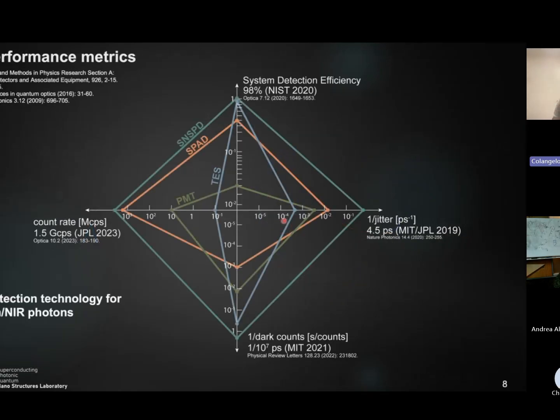Now, these are really, really amazing detectors. So they're the best detection technology for telecom and near-IR photons. And it's easy to claim. So here, I really like to show these plots where we have 4 detection metrics: the efficiency, the jitter, the dark counts, and the count rate. And these numbers here, not very important, but they're the record for each of these metrics. And I also want to mention that the jitter and the dark count record metric are actually from my own research. And we can see that the SNSPD covers the full area of this plot and beats all the competing technology in this area, for example, the SPAD, the transition edge sensor, and the silicon photomultiplier.